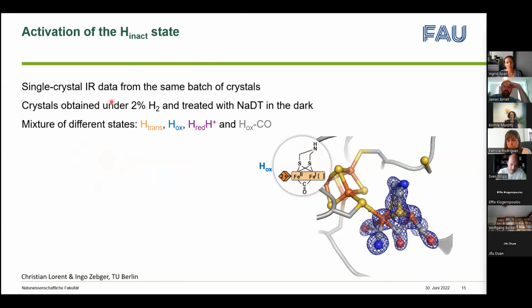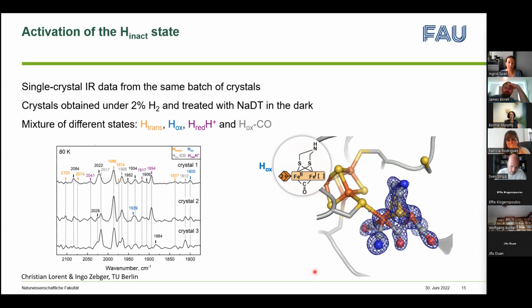And these crystals were obtained under 2% hydrogen and treated with sodium dithionite in the dark, because we see some damage if we expose the crystals for an extended period of time to light. And Christian's data actually showed that we are not in the H-intact state anymore, but we activate the enzyme to a mixture of different states. Some of them are H-trans.